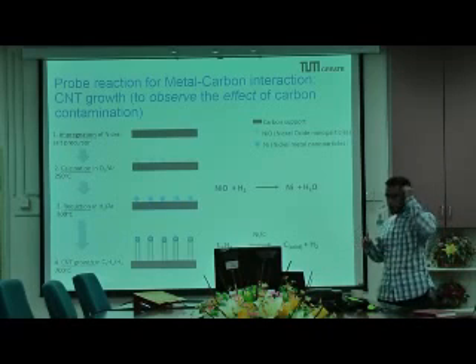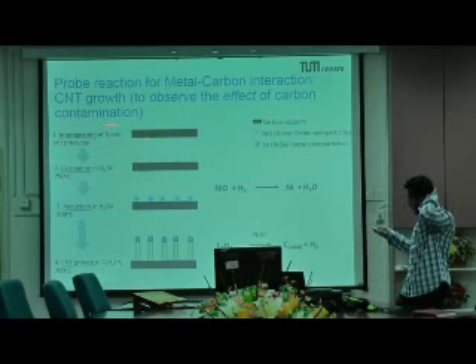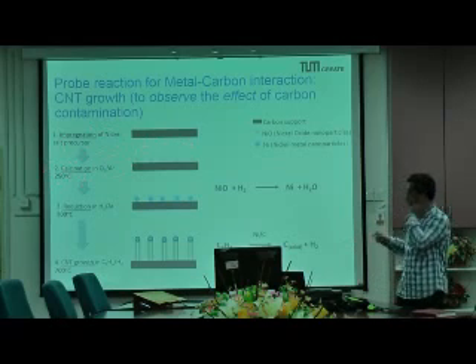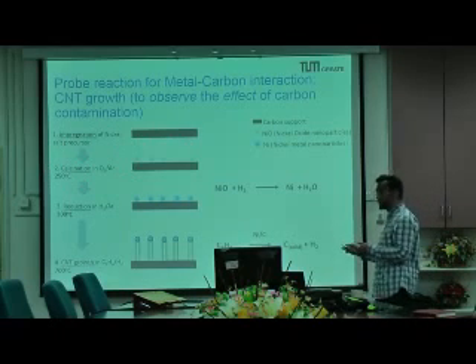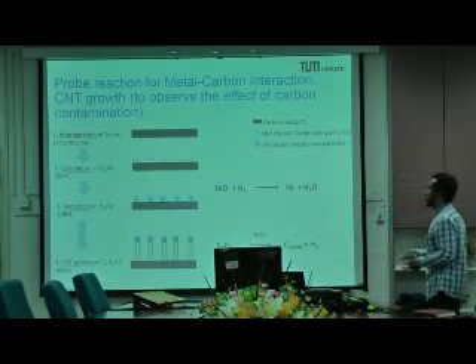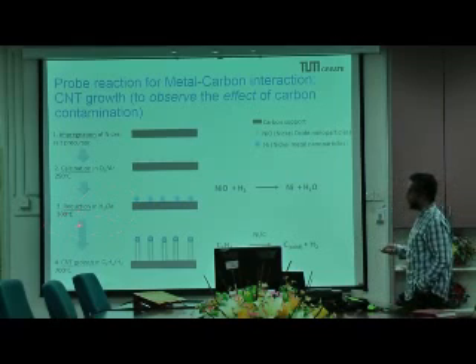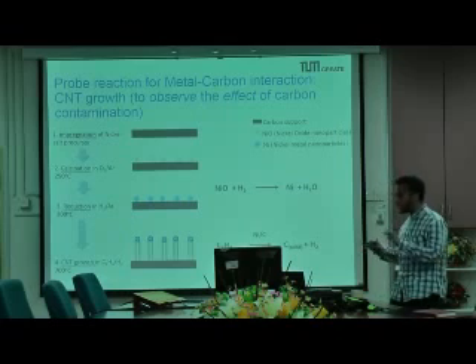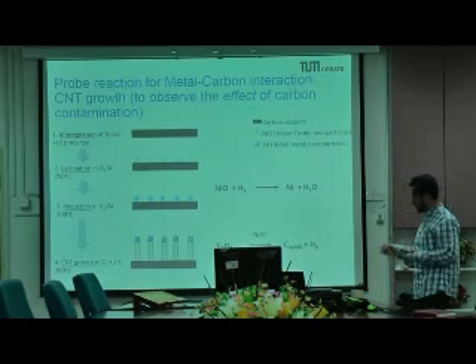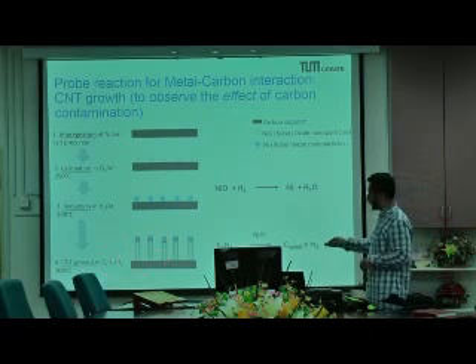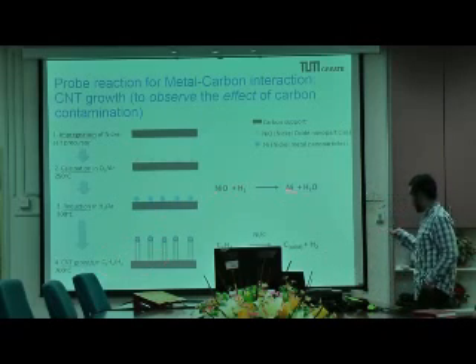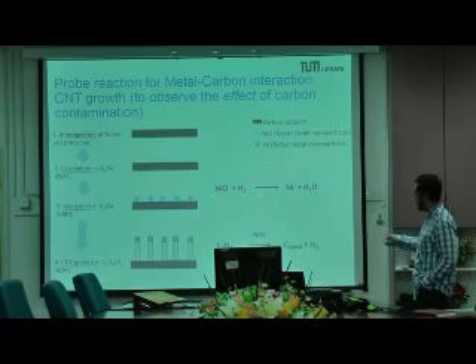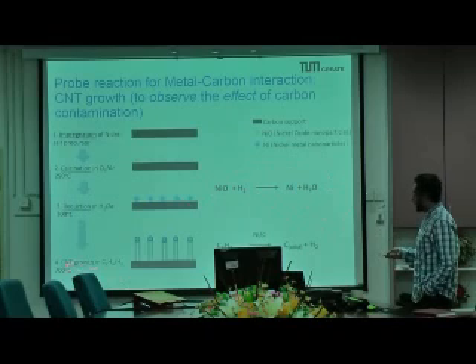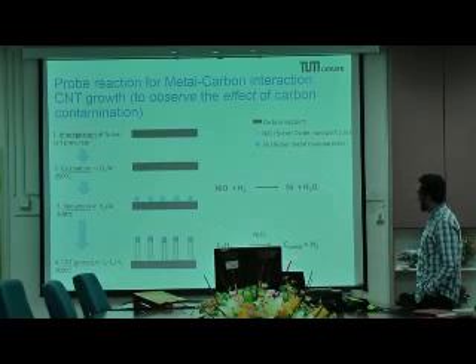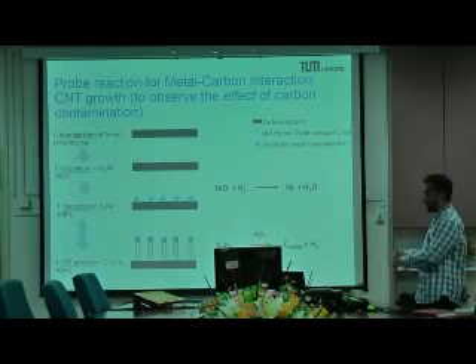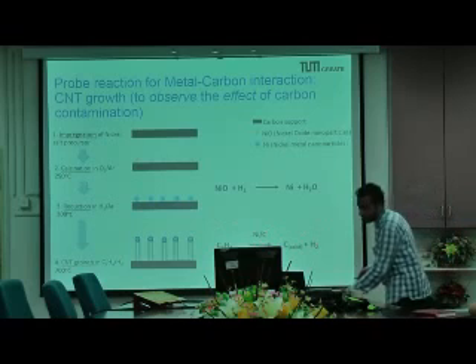The process, if you are familiar with this, is very simple. You deposit a material onto a carbon support, you calcine it in air, not high enough that it oxidizes the carbon, because again, this is a catalyst, so it reacts with oxygen. And you reduce this catalyst in diluted hydrogen at 300 degrees, and then increase the temperature and do the growth at 700. In reduction, this is the reaction that you get: nickel oxide is reduced by hydrogen to nickel and water. In nanotube growth, the empirical reaction formula is that you have a hydrocarbon source, the catalyst will form solid carbon nanotubes, and hydrogen.